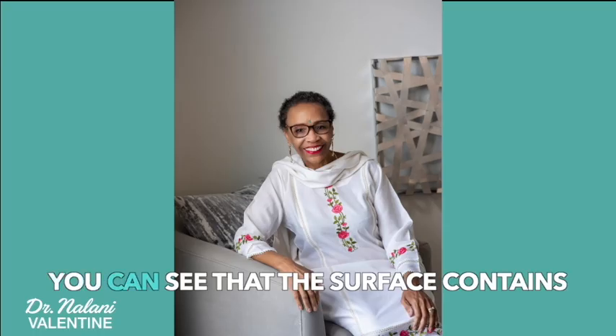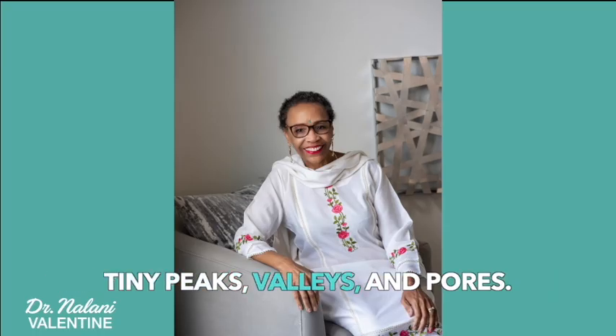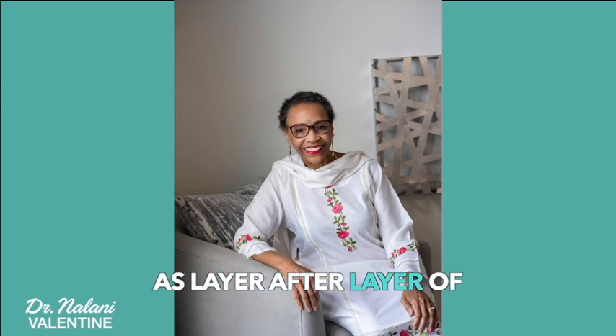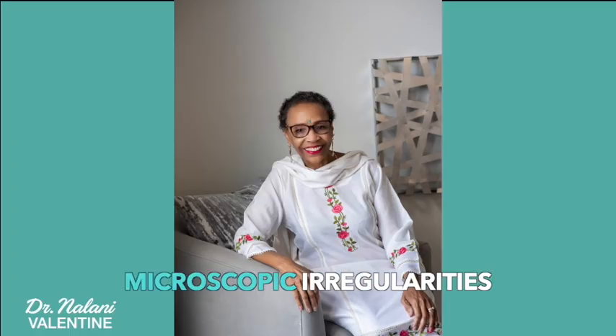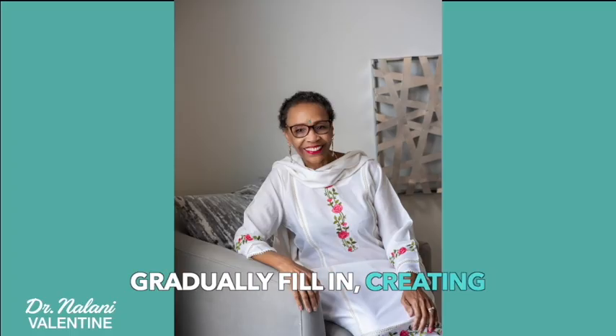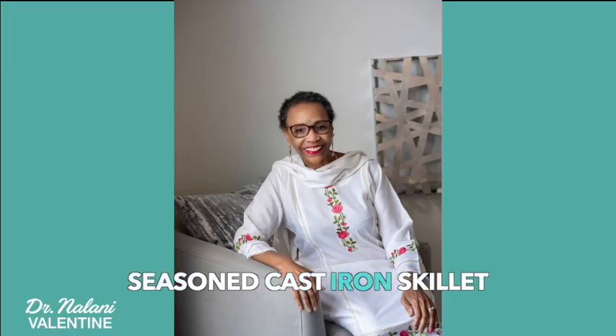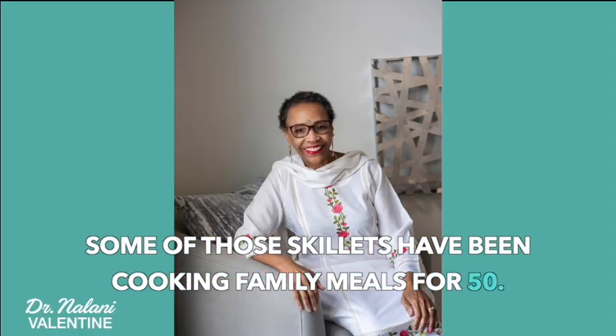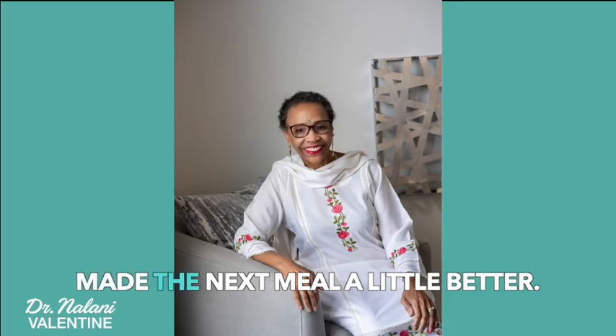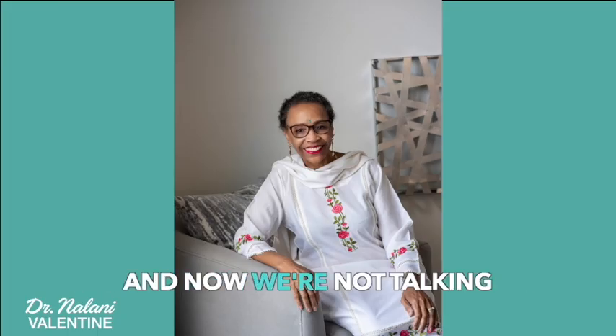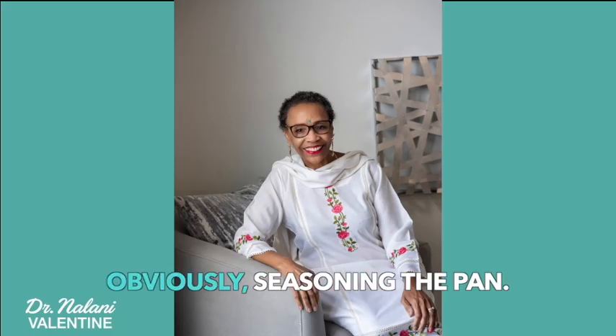Here's another little known fact. A cast iron skillet isn't perfectly smooth. When it's viewed under a microscope, you can see that the surface contains tiny peaks, valleys, and pores. As layer after layer of seasoning develops, those microscopic irregularities gradually fill in, creating a smoother cooking surface with each use. That's why an old, well-seasoned cast iron skillet often performs better than a brand new one. Some of those skillets have been cooking family meals for 50, 75, or even 100 years. Every properly seasoned meal made the next meal a little better. And now we're not talking about seasoning the food, obviously, seasoning the pan.